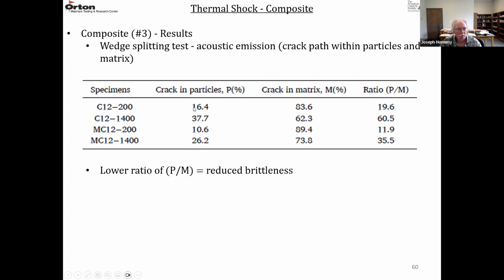So cracks in the particles in this 200-degree curing for C12, it's 16%, and it's 83% in the matrix. Then when you go up to the higher temperature after it's coked, more particles are cracking and less fracture in the matrix.